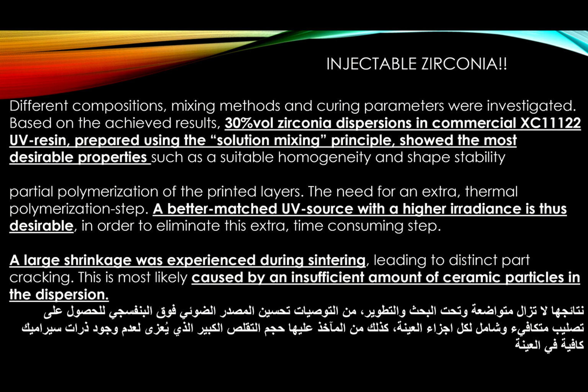Okay, now there are things to say about this. Using the solution mixing principles showed the most desirable properties. No problem. A better matched UV source with a higher irradiance is thus desirable because they figured that there is an issue in the light curing. It should be evenly distributed on the sample in a better way. A large shrinkage was experienced during sintering caused by an insufficient amount of ceramic particles in the dispersion. Like I said, we are far away from achieving anything with injectable zirconia.